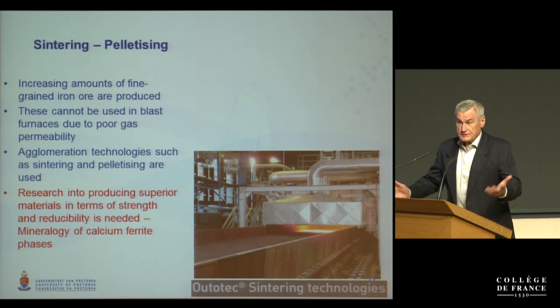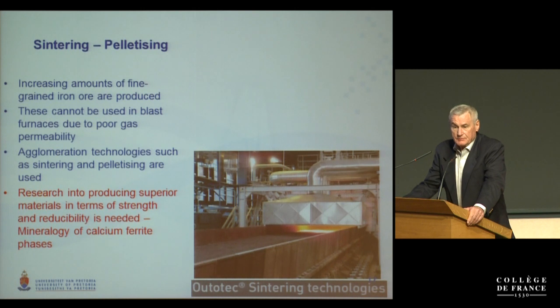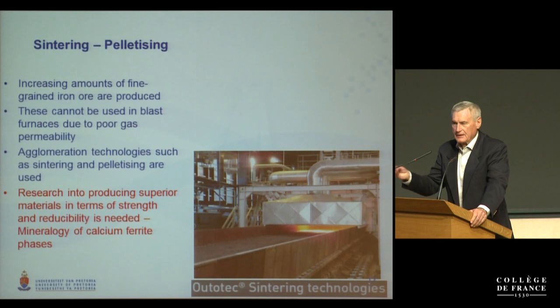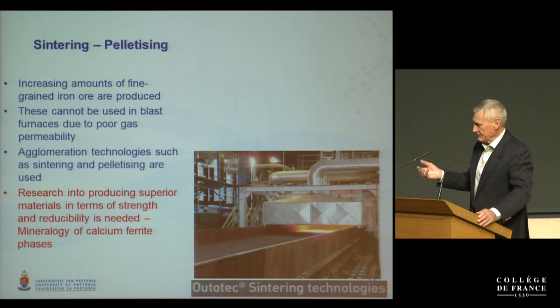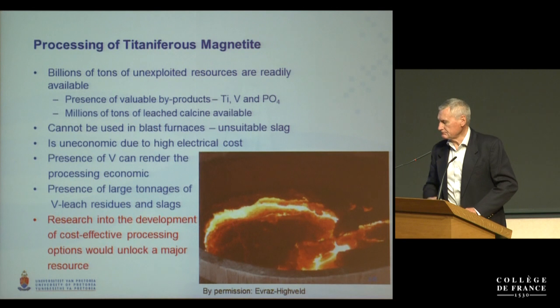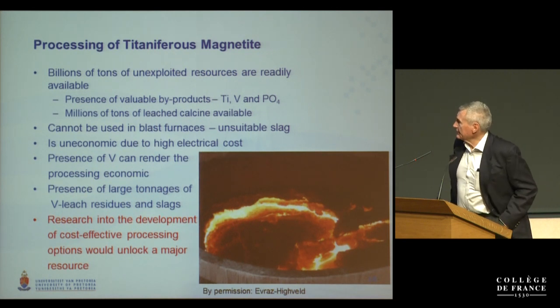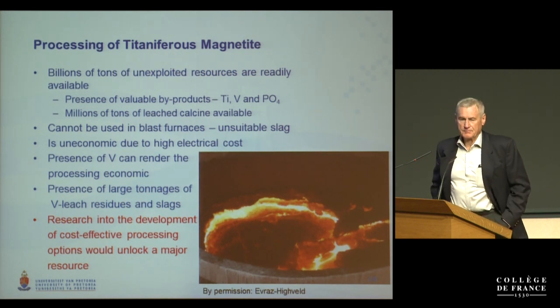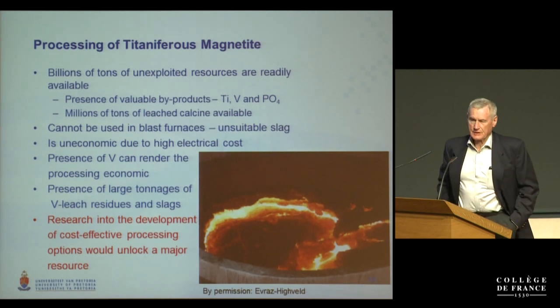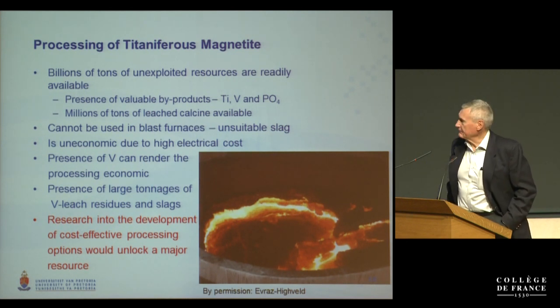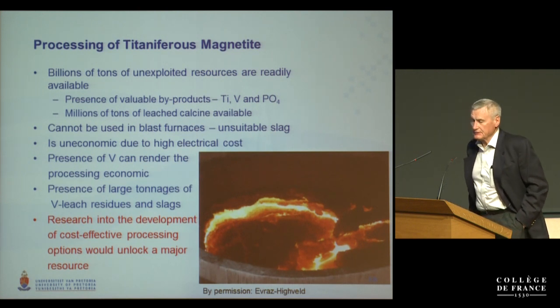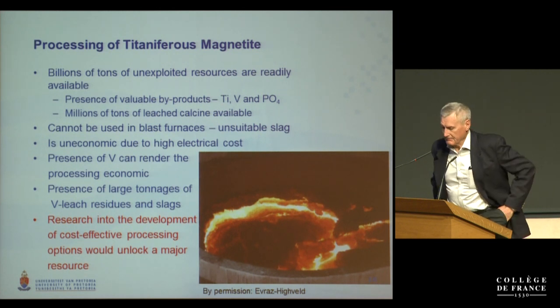And for instance, the Minas Rio deposit in Brazil, the iron ore deposit, pumps its very fine flotation concentrate about 600 kilometers to the sea. There it needs to be agglomerated. So there's a need for that. There's another one, processing of titaniferous magnetite. And here, quite a huge resource is lying essentially undeveloped. And they contain not only iron, but also titanium and vanadium.